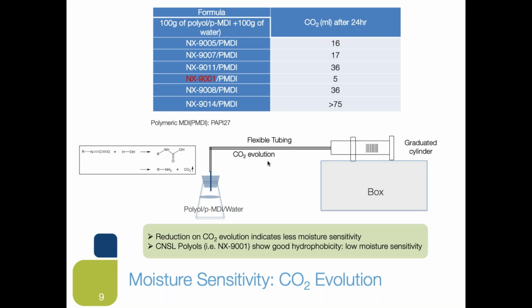One way to reduce the moisture sensitivity is to choose a polyol that can offer better hydrophobicity. So in this study, we simply mixed polymeric MDI with the polyol and then a lot of water. So this is a more exaggerated study. And from there, we collected the CO2 amount. NX9001, as you can see, has the least amount of CO2, meaning NX9001 offers the best hydrophobicity. Therefore, you can lower the moisture sensitivity of your system, followed by 9005 and 7, and then 9011.